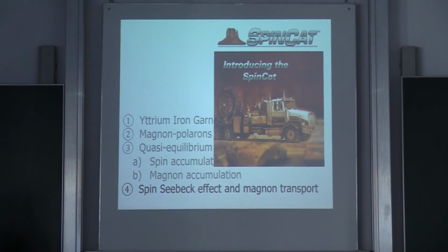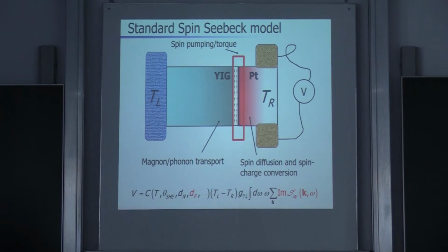So let's go from these general discussions to magnon transport, and then specifically the spin-Seebeck effect. As I mentioned before, the spin-Seebeck effect is the creation of a thermoelectric voltage by a temperature gradient. The sample usually consists of an insulator like YIG and a heavy normal metal like platinum. And we assume that there is a temperature gradient over the system.